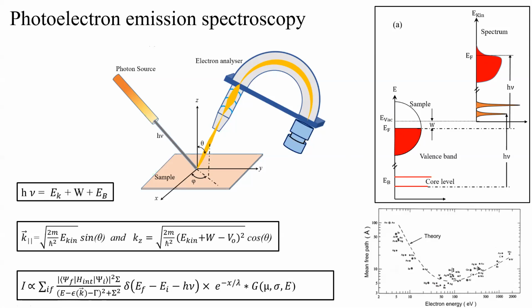Okay, so you are saying this comes from the experimental resolution factor and other. It has both. The broadening comes because of the spectrometer and the lifetime of the core hole that I've created. When you knock out an electron, you basically have a core hole at the sample position. There is a finite lifetime of that core hole. If it has a very low lifetime, you will see a very broad feature. It basically comes from the Heisenberg uncertainty principle. If the lifetime of that core hole is very small, you will get a large broadening in the energy scale. So because of these two reasons, we get broadening here.